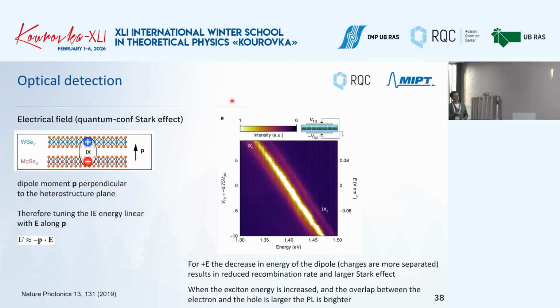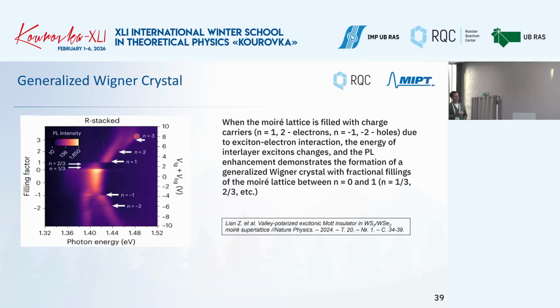That should be the case for the quantum confined Stark effect. But in the experiment, there is something weird going on. There is no linear dependence. There are some abrupt changes of the photoluminescence. And the reason is that there is the exciton-electron interaction that defines the changes.